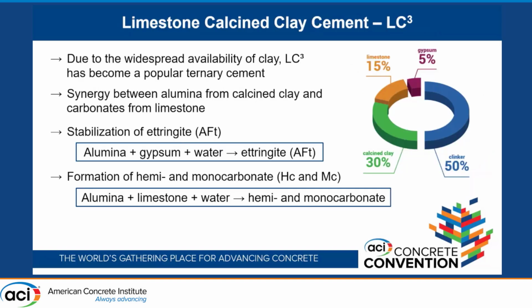And then a second look into SCMs, more recent, we have LC3, which is limestone calcined clay cement, which is a mix of limestone, calcined clays, some gypsum, and clinker. We're able to achieve a lower amount of clinker that way.